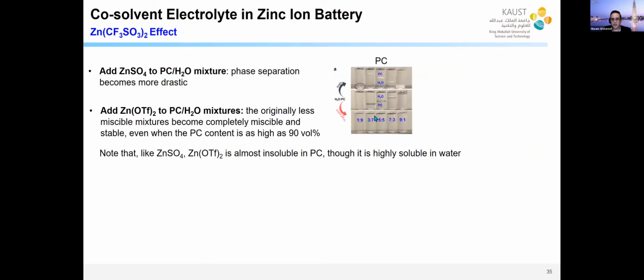So here's, for example, a group of vials. In the middle, you see water and PC, a two-solvent mixture. They are phase separated as you would expect, especially as you add more than 17% PC. If you add zinc sulfate, a common salt for zinc, this phase separation on top here becomes worse. However, if you add zinc triflate, this phase separation disappears and you form very nice solutions. Even if you add 90% by volume PC, you still have a very clear solution. This is surprising because, unlike zinc sulfate, this zinc OTF is almost insoluble in PC. But suddenly you can dissolve it in 90% PC.